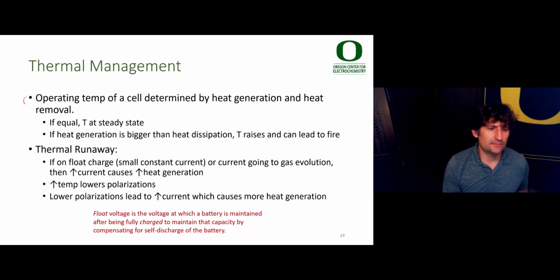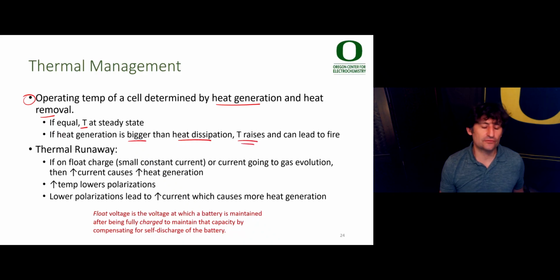Now, the operating temperature of a cell is determined by both heat generation and heat removal. When they're equal, of course, the temperature reaches a steady state. If heat generation is bigger than heat dissipation, heat continues to rise with time, and eventually the battery will overheat, and that leads to a fire. This can be thermal runaway. This type of thermal runaway can happen, for example, if the battery is on float charge, where you're applying a small constant current, or current is going to gas evolution. And then as the current goes up,